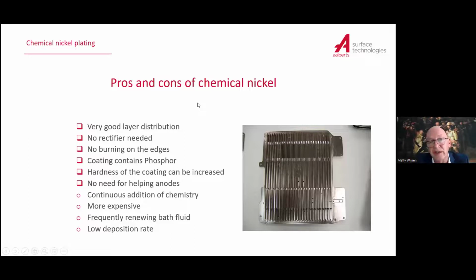Pros and cons. Chemical nickel has a very good layer distribution. That's perfect in that case. You don't need any rectifiers. You don't have any burning on the edges. The coating has phosphor, so you can increase the hardness, and you need no extraordinary measures for getting your layer everywhere.